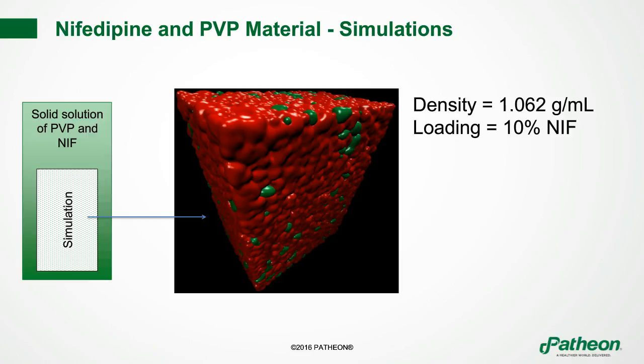And you can see that in red on the surface is the polymer, the PVP, and then the green blobs are nifedipine. For the most part, you've got what I would call a pretty good dispersion because you see that there are individual drug molecules here and there that are well separated from each other. And that's exactly what you want in a dispersion. You don't want agglomeration of drug molecules. You want the drug molecules to be dispersed completely within the polymer matrix so that when this system goes into water, it dissolves and the drug is released as individual drug molecules, so that there's no chance of nucleation and you can achieve a supersaturated state of your drug molecule in water. And that's exactly what we're looking for.